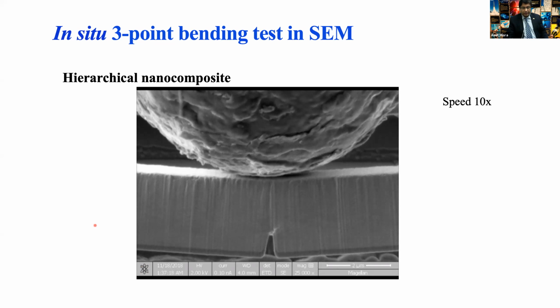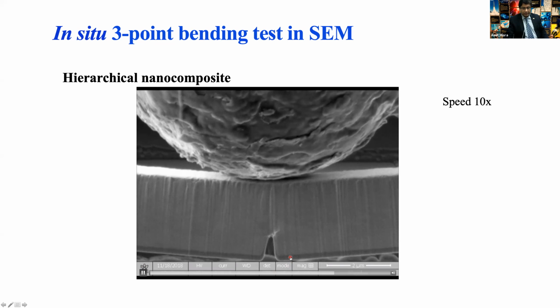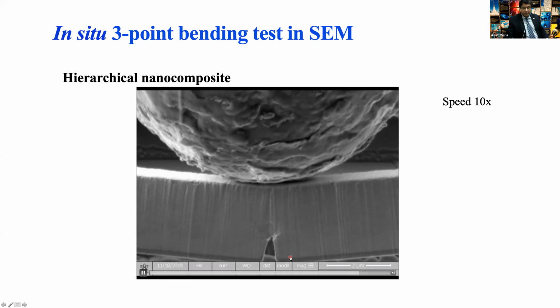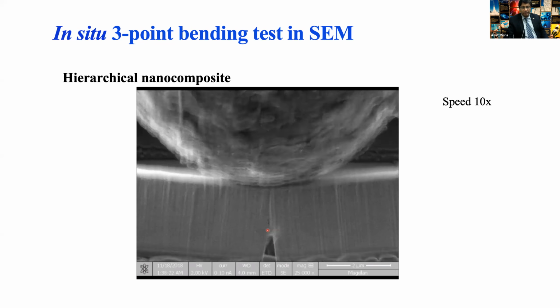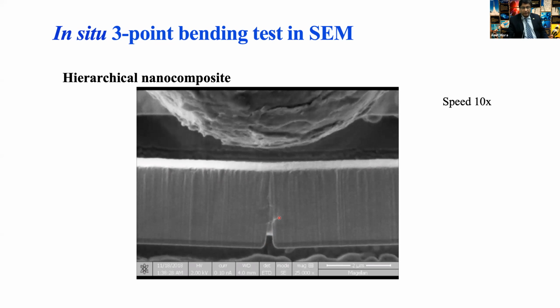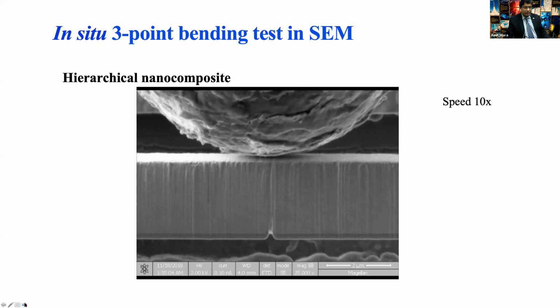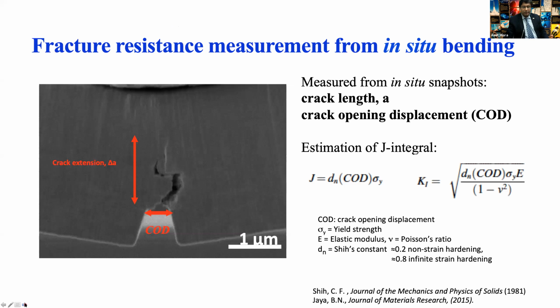You can see it right away that it is giving the indication of significantly enhanced crack growth resistance. The crack has popped, but the sample did not fail. The crack was able to meander, but we were able to preserve that sample and then section this and look at it in TEM. So we are able to do a FIB lift out and look at it in TEM.